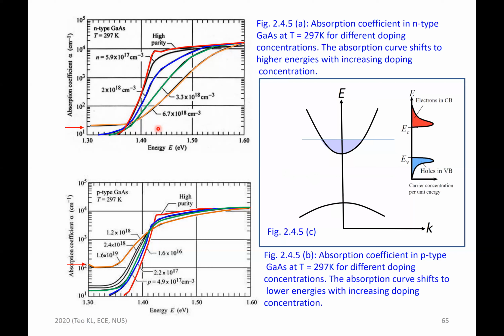Okay, so you can see that the absorption coefficient is reduced because many of the states in the conduction band are already occupied. If you move your Fermi level further up, more and more states are occupied, which means there are fewer available states for the electron to be promoted from the valence band to the conduction band. Eventually, they will reach a level where there are no available states for the optical transition, as you keep increasing the Fermi level. So the absorption coefficient actually decreases as the concentration increases. And this is indicative of the band gap narrowing effect.